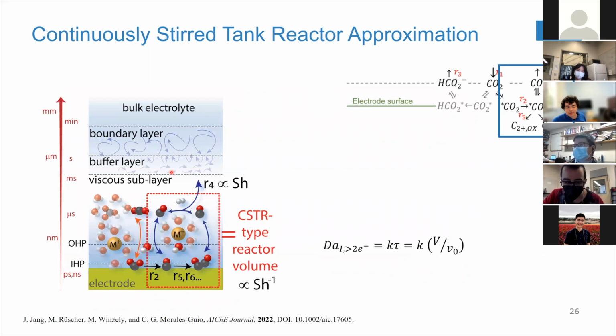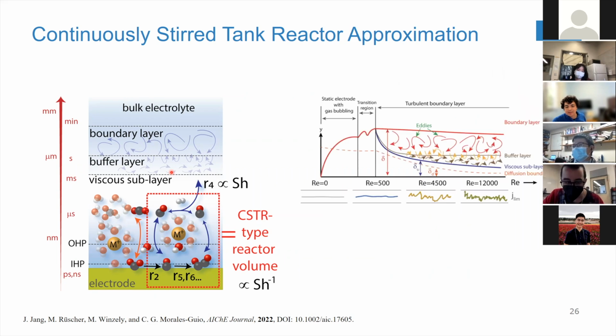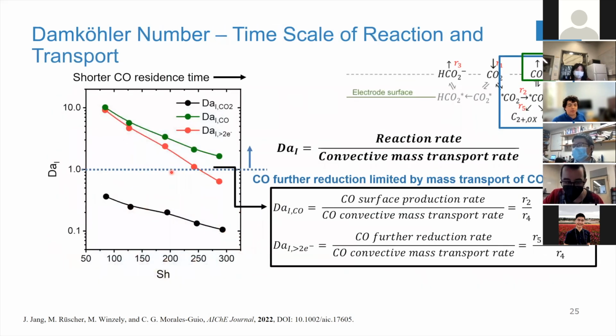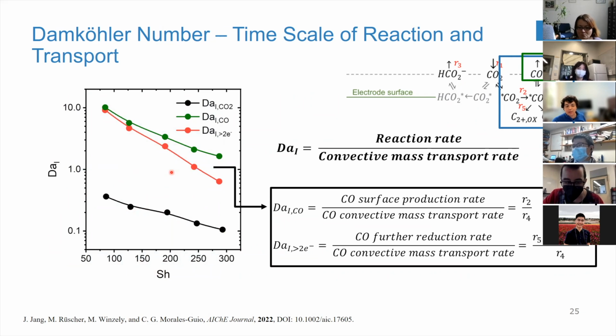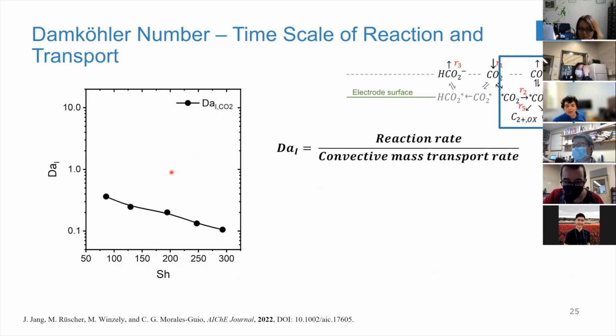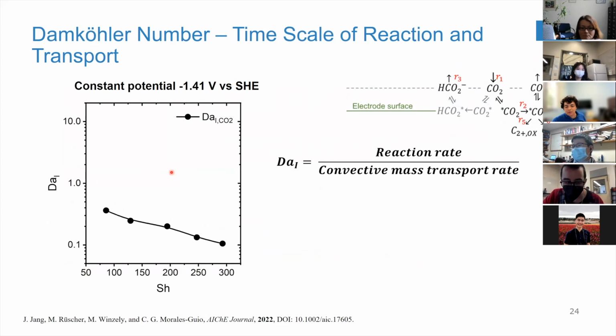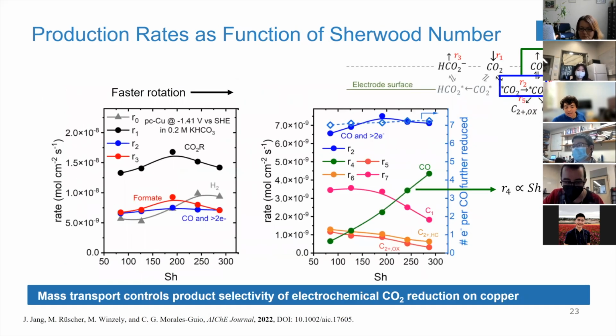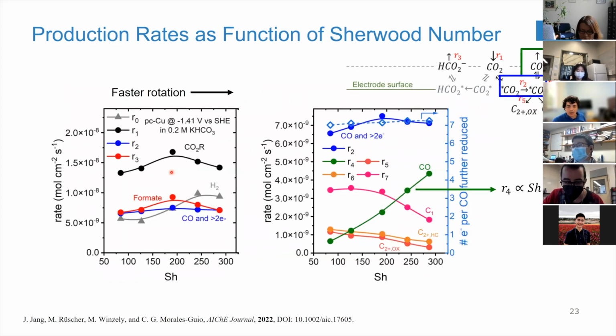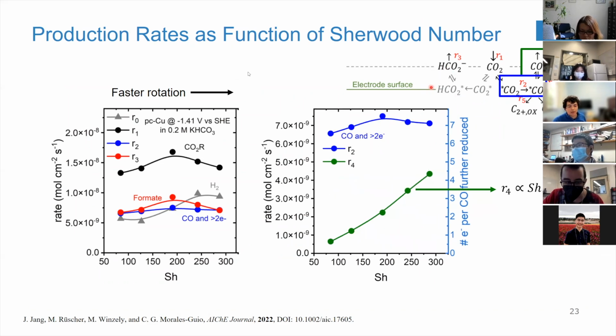But what we have said is that you can actually turn copper into silver if you want. Because, as I was showing before, as you increase the mass transport of CO away from the surface of the electrode, you actually increase the production rate of CO. So you can actually make copper look like silver if you transport the reaction intermediate fast enough.